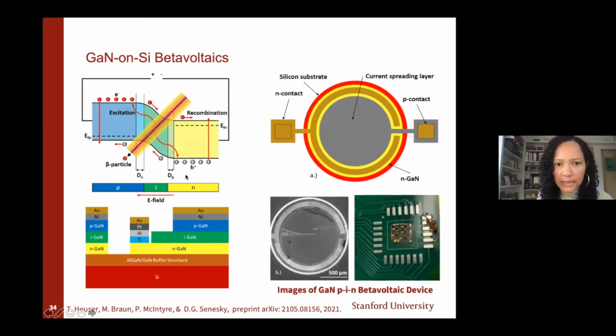A couple more minutes. So we can also harness radiation as a power source. And I just want to highlight, this is a beta particle coming in, and we have excitation of carriers and recombination. And this can create current or power. So we can harvest energy from low Earth orbit potentially. And we've done this through a gallium nitride PIN architecture. This is recent work. And we put the pre-publication up if anyone's interested.